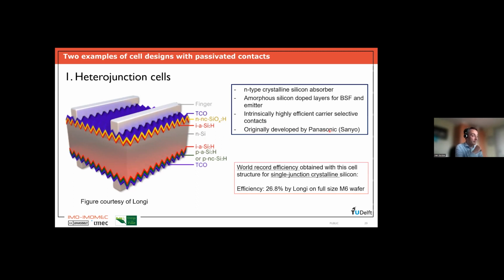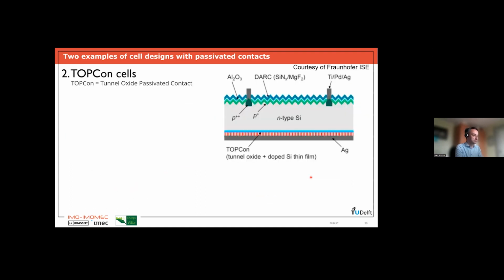And at present, the highest efficiency quite recently obtained with this type of device was by the Chinese company Longi. They have reached on a large wafer an efficiency of 26.8%. And this is actually the world record efficiency currently for a single junction crystalline silicon. So this is the best silicon solar cell we have ever made. It's 26.8%. So it's quite a lot. And you see clearly higher than what we can achieve with the PERC cell.